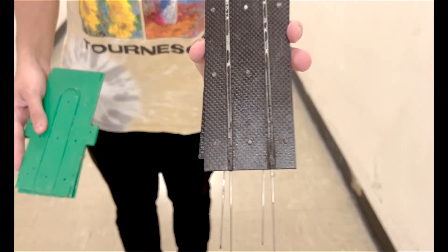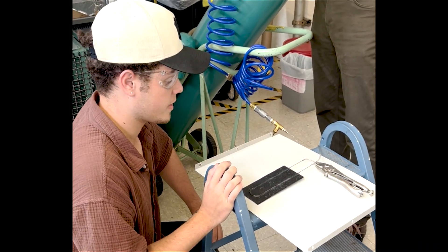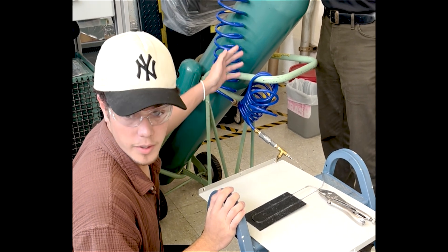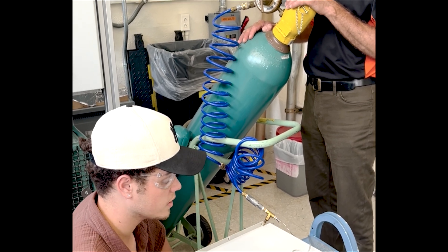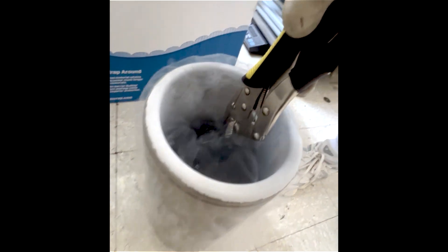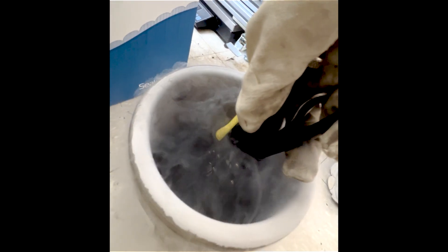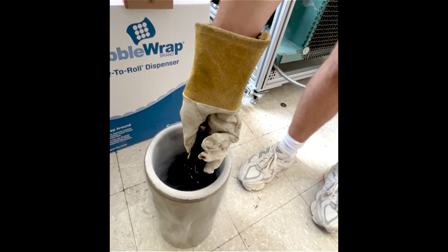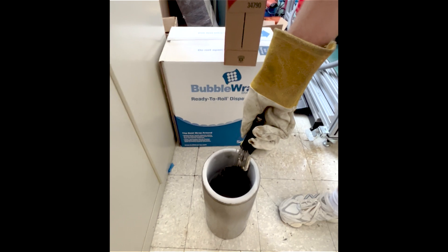This is a prototype carbon fiber bracket. We're conducting a pressure test on a carbon fiber tube sample, connecting to a helium gas pump and slowly ramping up the pressure to check for leaks and find the point at which it fails. In this experiment the carbon fiber prototype is also submerged in a bath of liquid nitrogen, where temperatures can reach as low as negative 196 degrees Celsius. This test is important to confirm the bracket can withstand the low temperatures normal inside embedded cooling systems and detectors.